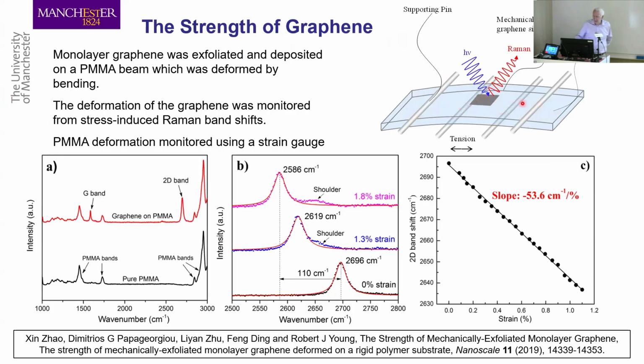We then deform the beam, which then deformed the graphene, and we looked at the behavior, and this shows you the setup. You can see this is the Raman spectrum of pure polymer. This is the Raman spectrum of polymer with graphene on it. And you can see the graphene, although it's only 1 atom thick, we can see the spectrum from it, although the PMMA was 3 millimeters thick. So it's a very strong effect. And if you look at this particular peak, undeformed, it's here, 1.3% strain, it's there, 1.8% strain, it's there. Massive shift of the band. And if you plot the peak position of that band against strain, you get a slope of about -55.